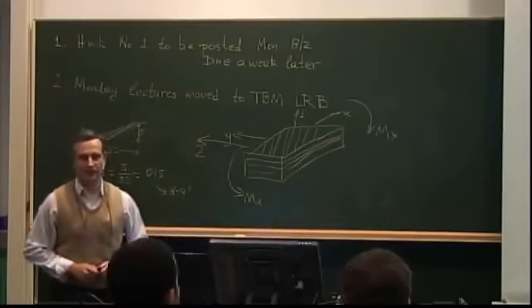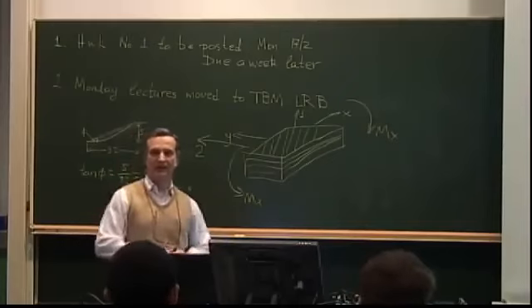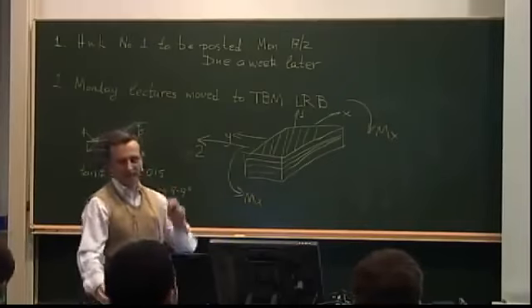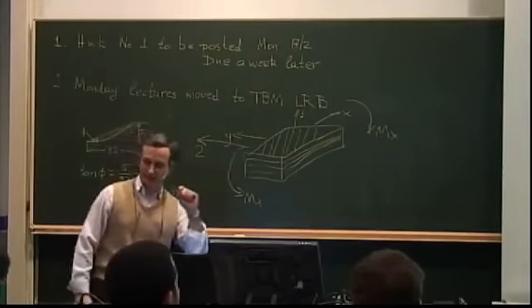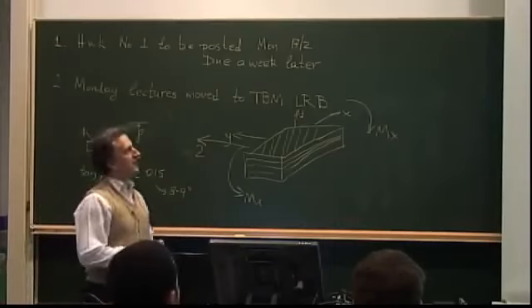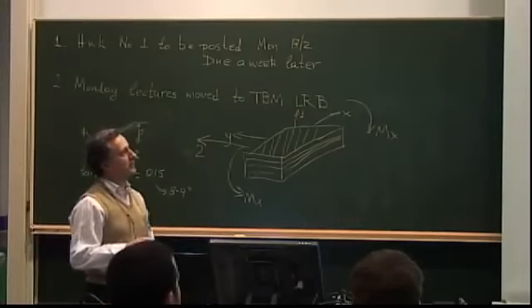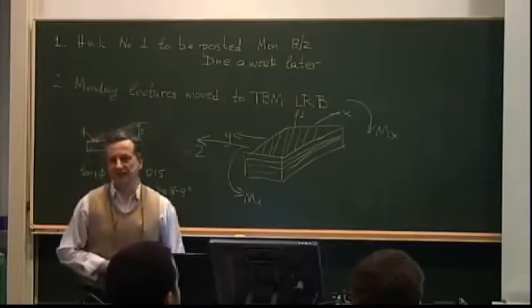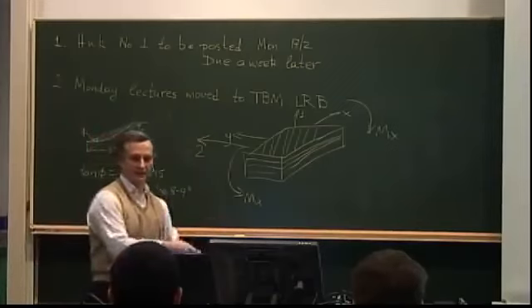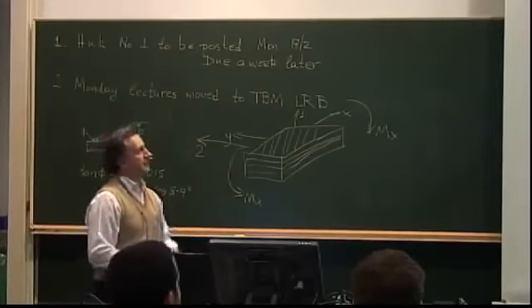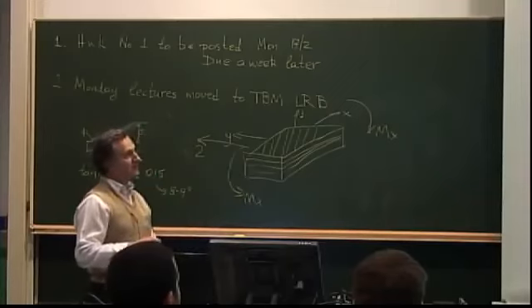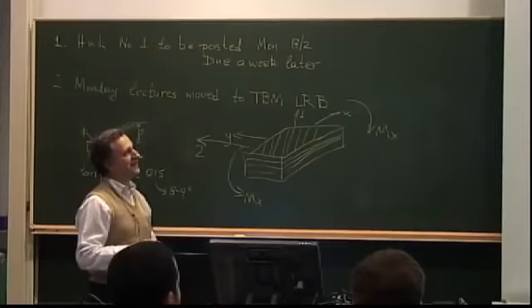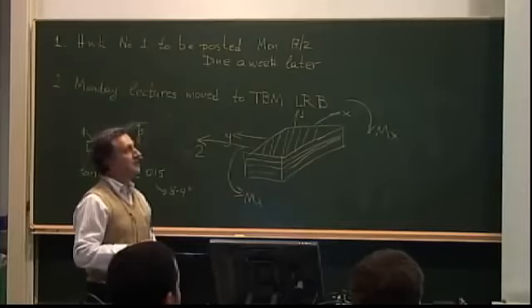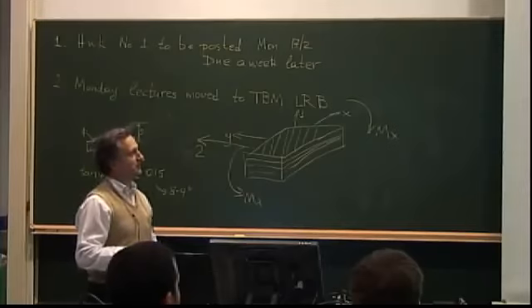I mentioned the gentleman, John Hart Smith, who is the main attacker of the Tsai-Wu criteria. Look at this. This is actual publications, and if you are as famous and as smart, you can get away with this. The irrelevance of most composite failure criteria to conventional fiber polymer composites is claimed to have remained undetected. Basically, he's saying the composites fail in a completely different way than these criteria imply. Then the Tsai-Hill failure criterion. Nothing in Hill's work addresses more than one mode of failure, and he should therefore be spared the ignominy, this is a New Zealander speaking, of association with the many abstract mathematical failure theories for composite materials. Yet, in the UK and Europe, Tsai's misinterpretation of Hill's theory of anisotropic plasticity is referred to as the modified Hill theory.